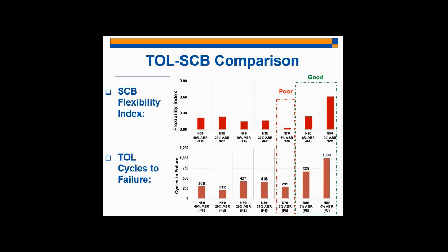Well, not currently, but that's actually what we're working on right now. We do hypothesize that the field fracture process zone is more similar to the 25 degrees Celsius, and we're confirming that with the DIC work currently. You want it to be more than just a leap of faith. Sure. And I think what would help is if you had a similar ranking in the materials, as you work your way toward a more economical and practical test, which is accomplished by running at 25 degrees so that you can do it in your Humboldt load frame, rather than worrying about an environmental chamber.